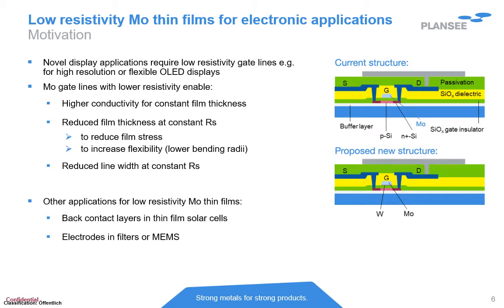this would enable a lot of benefits, like higher conductivity if you want to achieve a constant thin film thickness. But of course, you could also reduce the thin film thickness at a constant Rs, which is important to reduce thin film stress, but also to increase, for example, flexibility when you have a bent substrate. And of course, you have a reduced line width at a constant Rs.